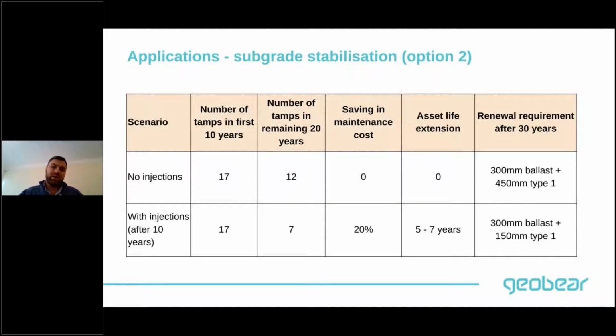And obviously, you haven't done any cost saving or asset life extension, and your renewal requirement is quite high. You still need the 300 mil ballast plus 450 mil of type 1. However, if you decide to carry out the injections after 10 years of operations, in the first 10 years, you have 17 tamping cycles. But in the last 20 years, after you intervened, you've actually reduced the tamping cycles from 12 to only 7. And that will translate into roughly 20% saving in maintenance costs.